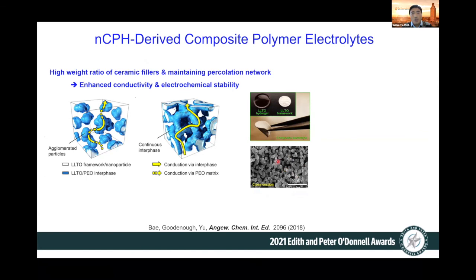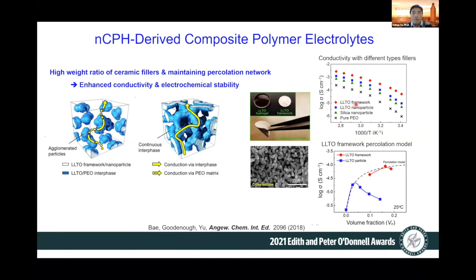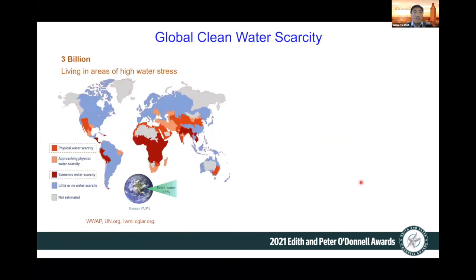This is an SEM image showing these interconnected ceramic fillers connected through the hydrogel network, and it's very flexible to work with. And you can see from our electrochemical characterization the different types of mechanism: one is with the gel framework, and then these random particles and other control samples. So you can clearly see our gel-derived framework offers the highest ionic conductivity, and the percolation is actually at a much lower volume fraction. So we can actually achieve the desirable room temperature 10 to the -4 Siemens per centimeter for solid state batteries. So let me use the next about 10 minutes to talk about other applications.